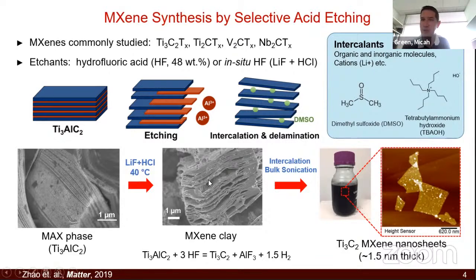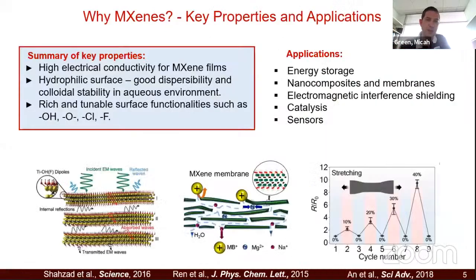You can imagine a book with every third page removed would look like this, a series of 2D sheets that are kind of connected together. And then you can intercalate with solvents and then delaminate or exfoliate into nanosheets and make these really nice nanosheet dispersions like what you see right here. And so there's lots of research on this. The reason people are excited about them is they're mechanically strong. They can be used for barrier properties, for energy storage. They're electrically conductive. So they're an exciting new material, and there's a lot you can do. One of the things that has kept people from doing more work in this area is the fact that using hydrofluoric acid is very dangerous, and a lot of people are not comfortable doing it. So that's definitely slowed things up.